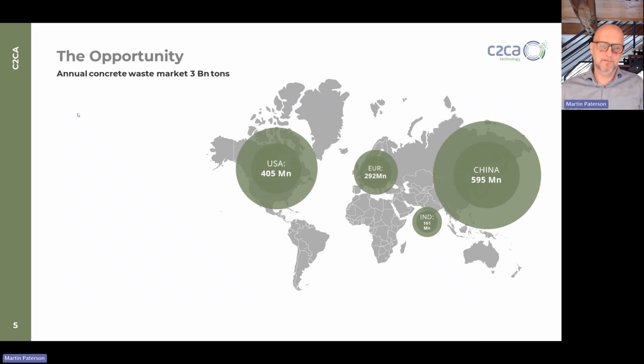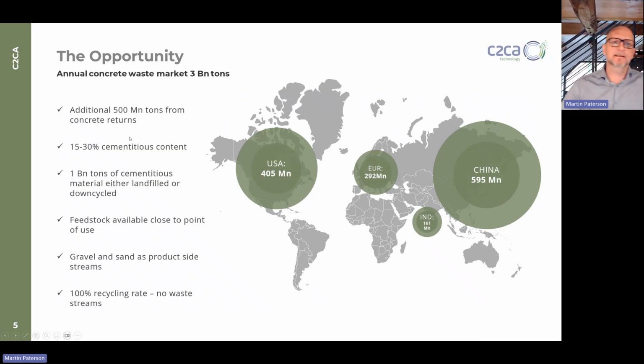And the positive aspect of this is that 15 to 30% of this feedstock is cementitious, of course, depending on the application of the previous life of the waste concrete. So if you make a rough calculation, we're talking about a feedstock of roughly 1 billion tons cementitious material, which is at the moment being either landfilled or downcycled. Very few applications where it's been upcycled or used as a filler in concrete.